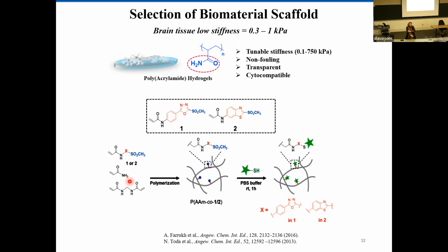So what we wanted to do was couple this IKVAV peptide covalently to polyacrylamide hydrogels. To do that, I designed two different new acrylates based on methyl sulfone chemistry. So this is the methyl sulfone. I designed two new acrylates that we can copolymerize with polyacrylamide hydrogels, and then we can covalently functionalize our peptide at room temperature in PBS without any issue.